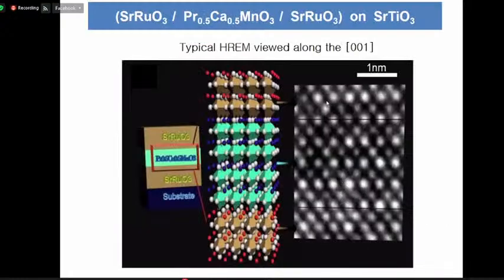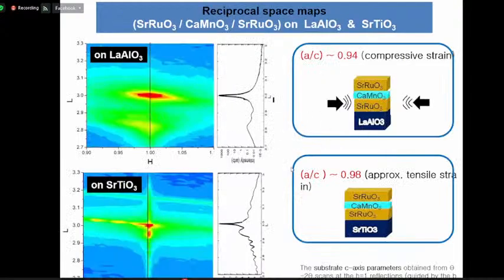Okay, this is a TEM image. This one also shows the diffraction structure, and from this we know lanthanum aluminum oxide gave strong compressive strain. Strontium titanium oxide also gave us tensile strain, but it's almost one, while their case is much stronger.